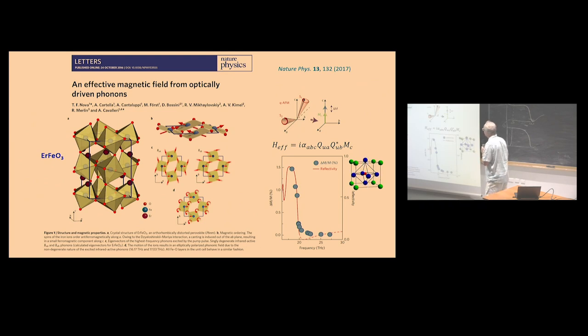Well, another possibility is how to control magnetization. This group, again Cavalleri, pumped erbium ferrite, and again they excited a high frequency phonon, which here is seen in reflectivity, showing that at this peak it's close to the transverse optical phonon. So when they excite this phonon, they observe a change of magnetization.